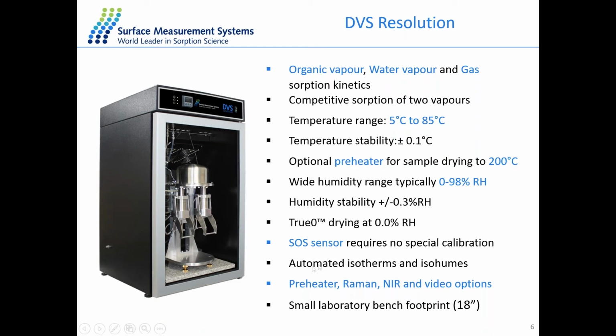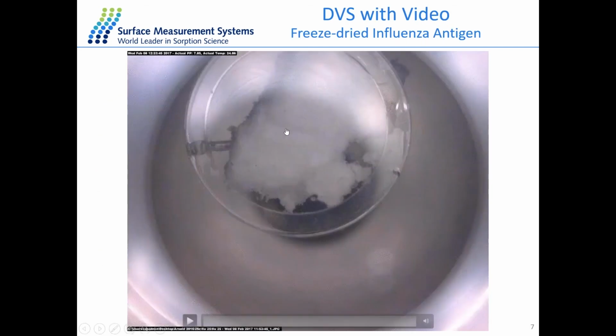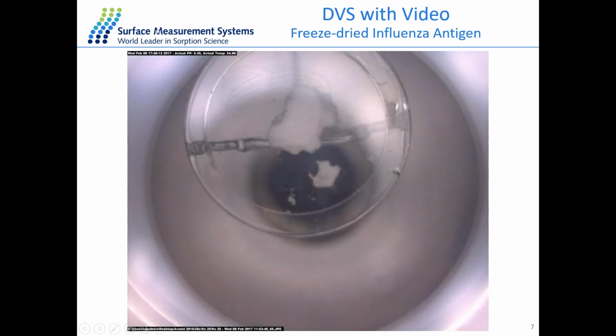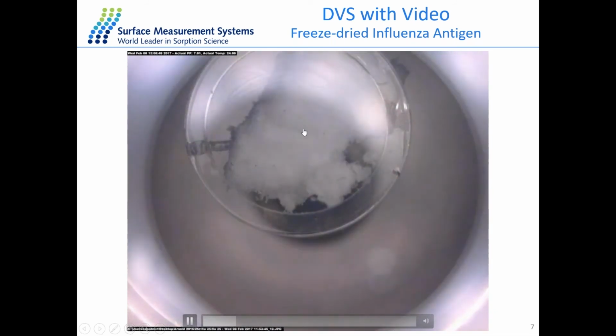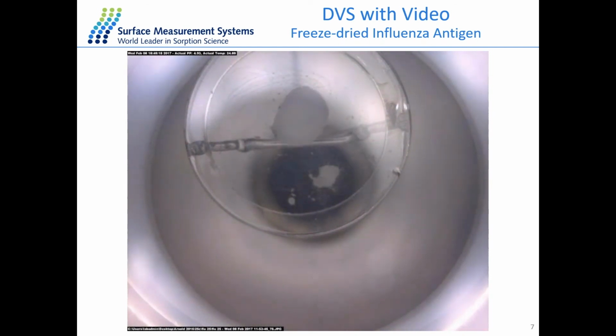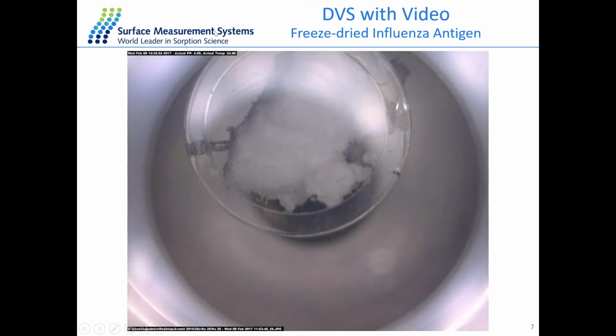And some other accessories can also be integrated with the system. For example, at the same location as the preheater, we can also install a video camera that takes the sample image at the end of each step, or takes the sample image at a fixed interval of time. And in that case, you can have a very clear view of the sample changing in nature or changing in different forms. So for example, here is an example of a freeze-dried material. And as you can see, at a certain point of humidity, which has the legend here on the right-hand side, the sample just collapses, shrinks, and then goes to the liquid form. So we can get the critical condition of the humidity as well as the temperature for the storage of this freeze-drying material.